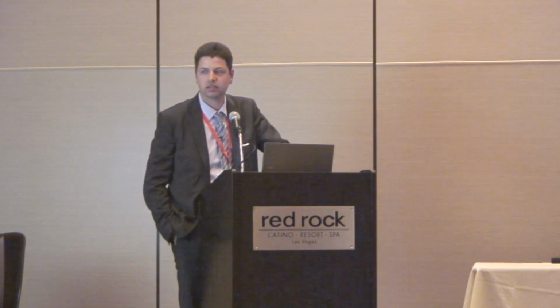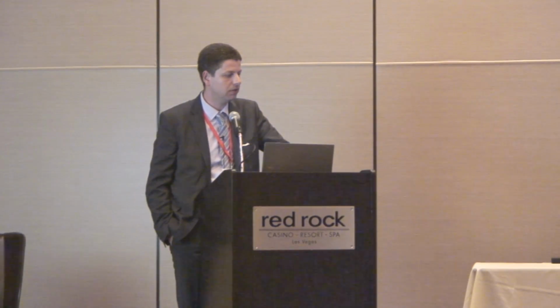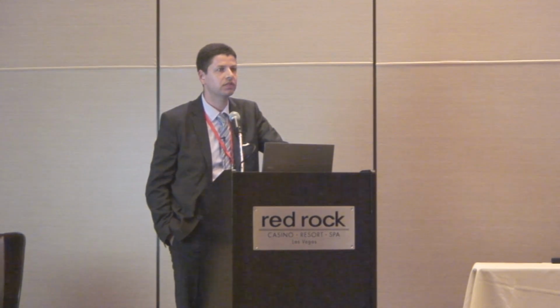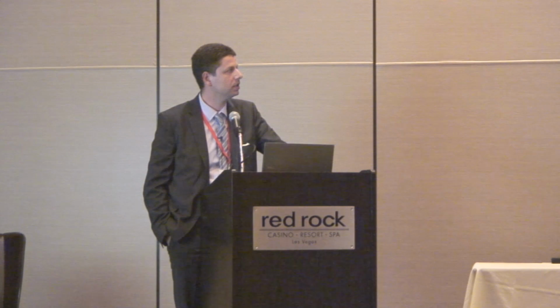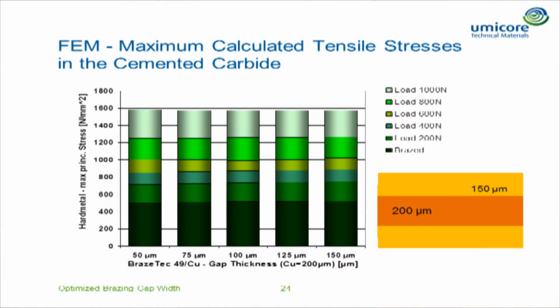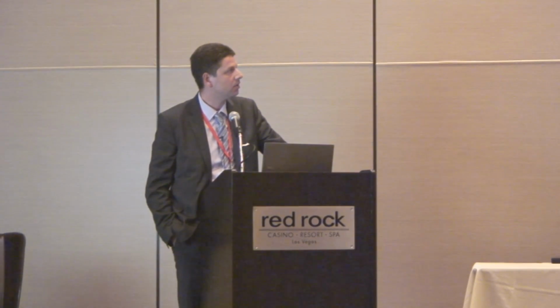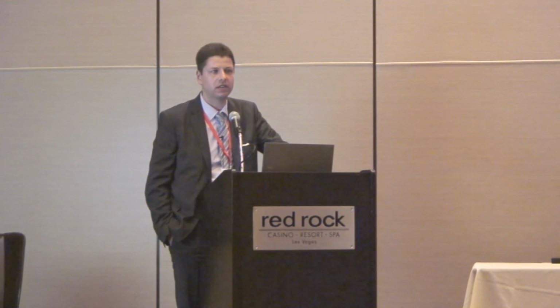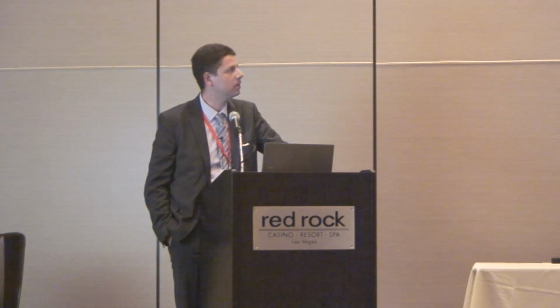When we now look at the results, we found something different. We're now looking at the maximum tensile stresses in the cemented carbide. To explain how the calculation was done: the interlayer was always set to 200 microns, and we always changed the brazing alloy layer. As you can see here, it was always increased. But the size of the gap does not have any effect on the stresses in the cemented carbide.